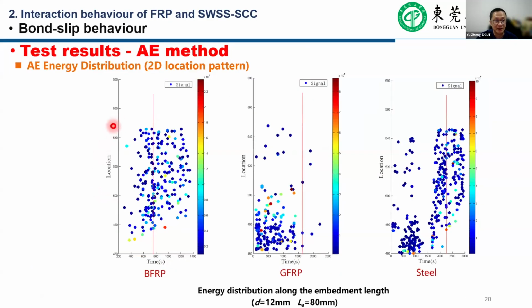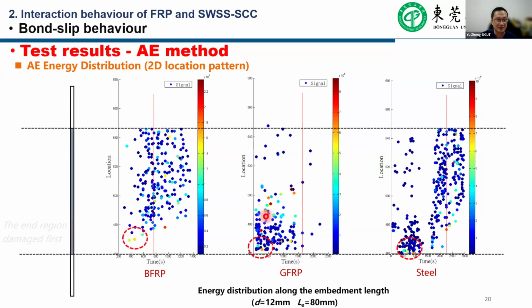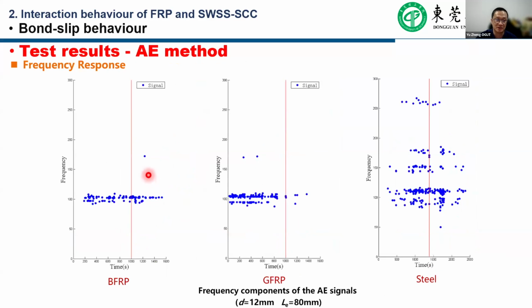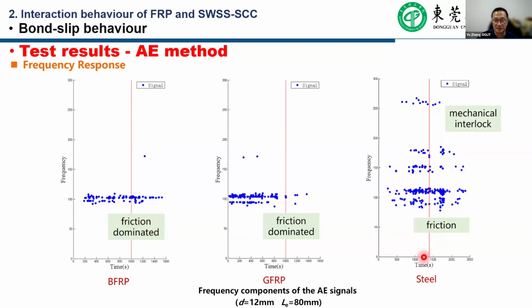And in the third part of this study, we try to use the AE method, the acoustic emission method, to identify the initial damage location in the bond test. We can identify the initial damage accurately. It's in the part close to the load applied. And furthermore, we also can use the method to identify the failure modes. We can find that for the FRP reinforced specimen, the failure mode is friction dominated. But for the steel one, it is friction combined with mechanical interlock, based on the signals from the AE methods.